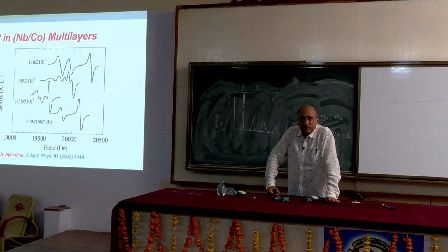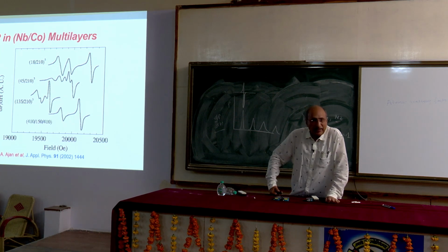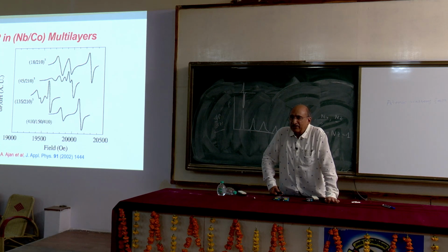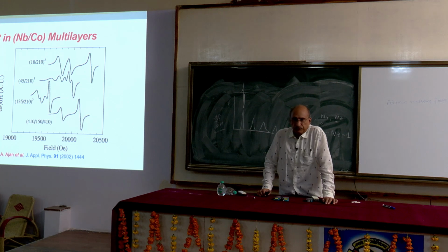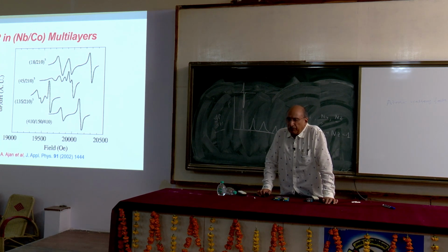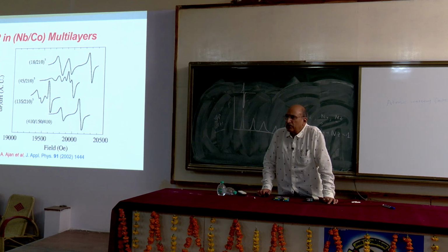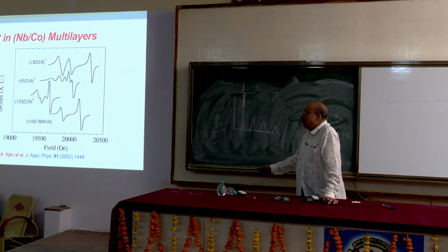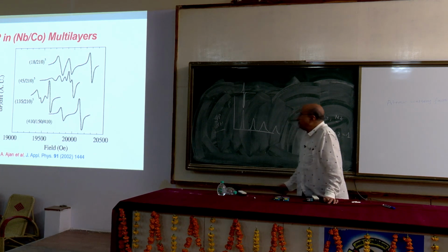Ideally speaking, the model that we have been talking about is not workable for a magnetic non-magnetic layer, but what I had done is assume that the niobium layer is replaced by an interfacial anisotropy and applied the same condition. Some people commented that we should have applied magnetostatic boundary conditions, which are much better, but we didn't want to do it. Our idea was to show that even with a thickness as large as 135 angstrom of non-magnetic material, the cobalt layers are still coupled. Resonance clearly shows.